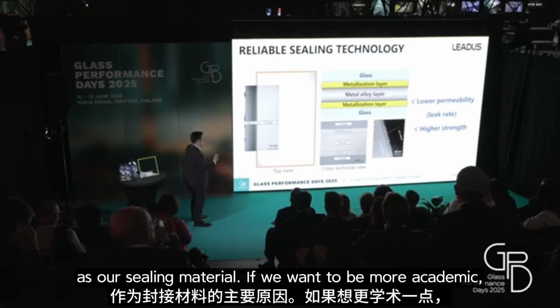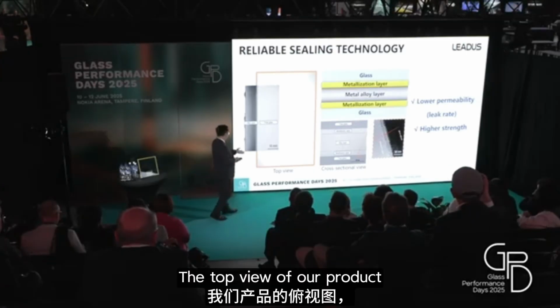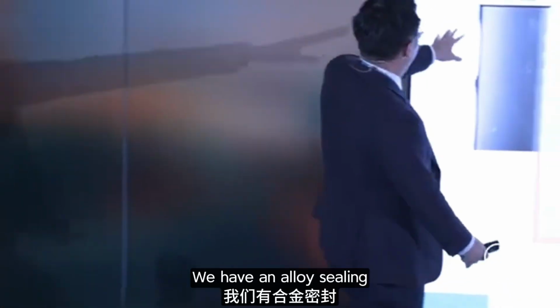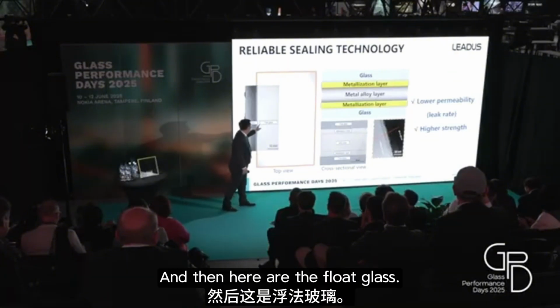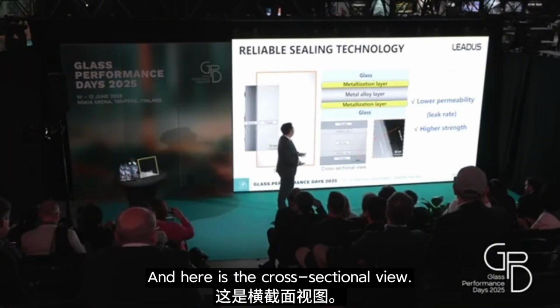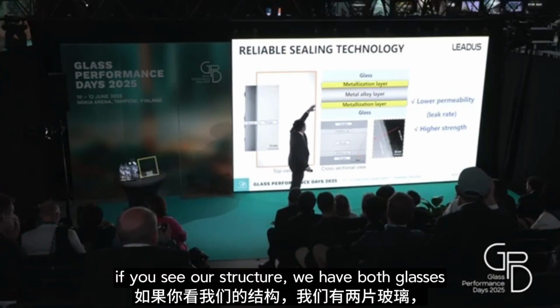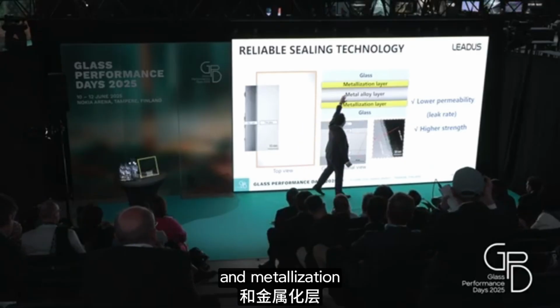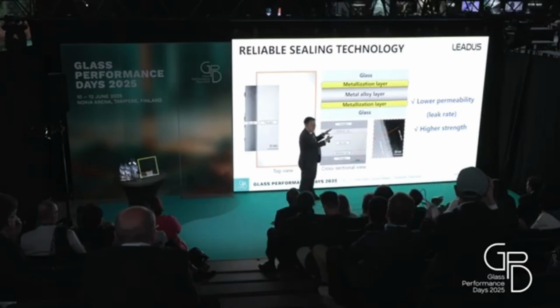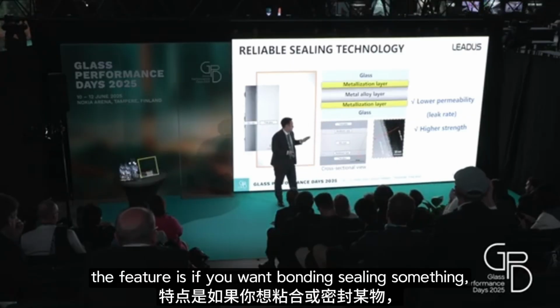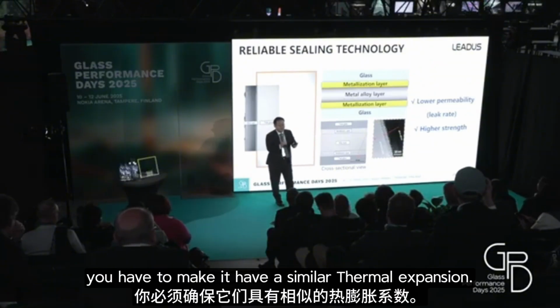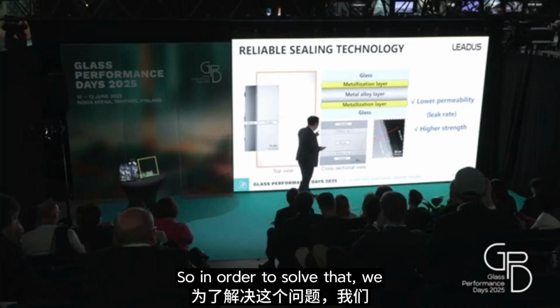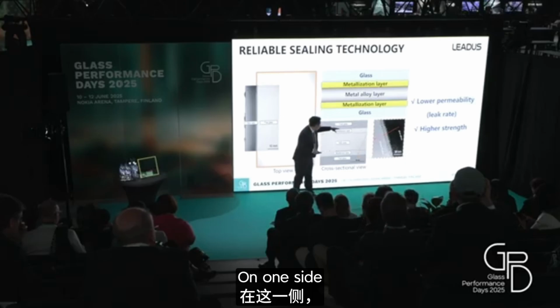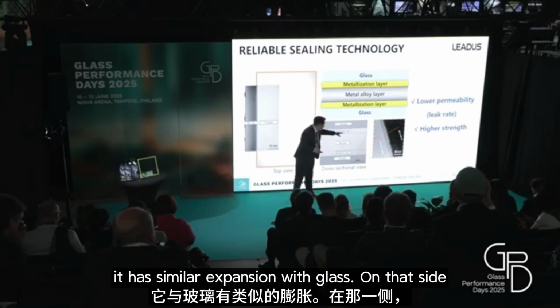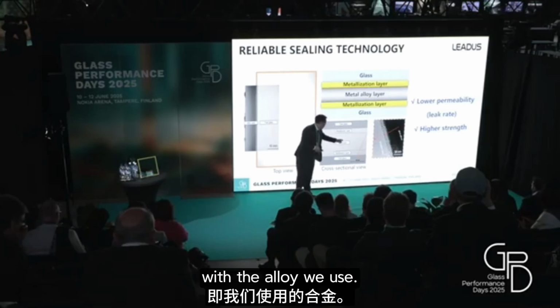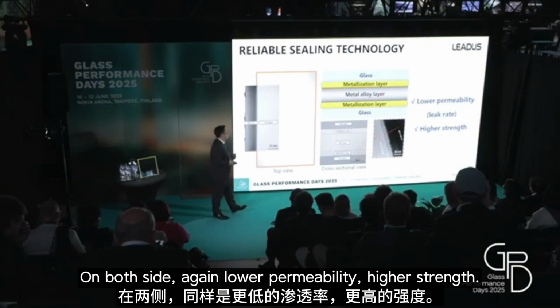If we want to be more academic, here are several pictures. The top view of our product, which we display over there, has an alloy sealing around the edge, and then here is the float glass. And here is the cross-sectional view. In our structure, we have both glass and a metallization layer on each glass. If you want to seal something, you have to make sure it has a similar thermal expansion. To solve that, we have a metallization layer. On one side, it has similar expansion to glass. On the other side, it has similar expansion to metal, the alloy we use on both sides. Again, lower permeability, higher strength.